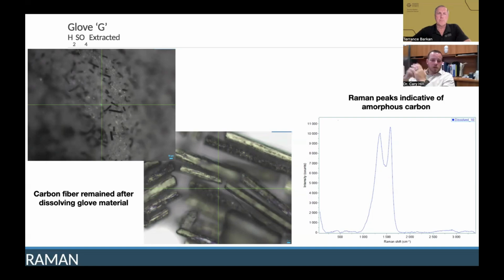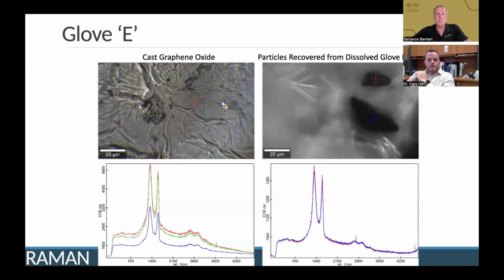Carbon fiber does not dissolve in sulfuric acid, and so that's why it's able to remain, while the other polymeric material, in this case probably a nylon of some sort, did dissolve. And so we have this carbon fiber there. You see those peaks? They're indicative of amorphous carbon. So some varieties of carbon fiber can be crystalline, others are amorphous. This was an amorphous variety.